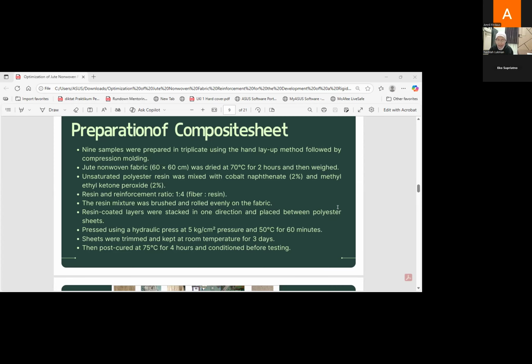And the next is the pressure, using a hydraulic press at 5 kilograms per square centimeter pressure at 50 degrees Celsius for 1 hour. Sheets were trimmed and kept at a stable temperature for 3 days. And the last is post-curing the composite at 75 degrees Celsius for 4 hours, and then we can test.